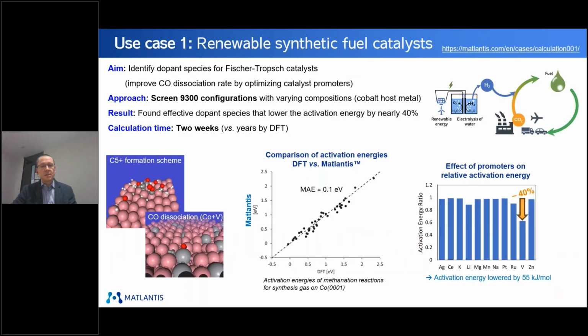This is the first use case I wanted to show you. It is a very simple synthetic fuel catalyst example. Here the goal is to produce something out of CO that would be more interesting, a higher value chemical such as C5+. More than 9,000 configurations were screened to find a catalyst promoter to decrease the activation energy of this reaction, the CO dissociation. And this was done with Matlantis in about 2 weeks. If you do this with DFT, we estimate it will take you a year or more.